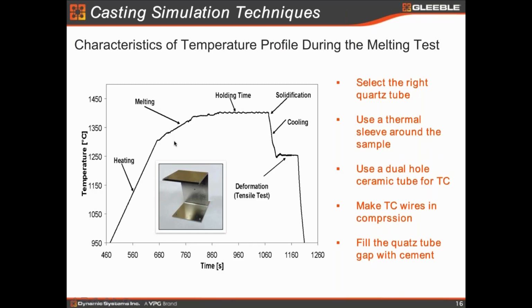Okay, firstly, before melting, I would definitely suggest you to slow down the heating rate, because otherwise the control of the liquid will be tough, right? As you can see, we have a lot of holding time. You can manually adjust the melting temperature or casting temperature, and then you can control solidification.